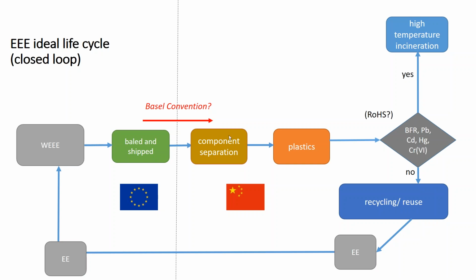And here we sort of turn a blind eye, but what happens, or what is supposed to happen, is the material is separated into plastic, metal, and so on. And the plastics are supposed to be divided according to whether they are compliant with the RoHS or not. Specifically, if they have brominated flame retardants, lead, cadmium above those restricted values, they should be incinerated at high temperatures. If they contain these in small quantities or they're not detectable, then they can be recycled, and ideally they should be recycled back into electronic equipment. And then we should in theory have this closed loop. We're keeping control of these contaminants and eliminating any anomalies here.